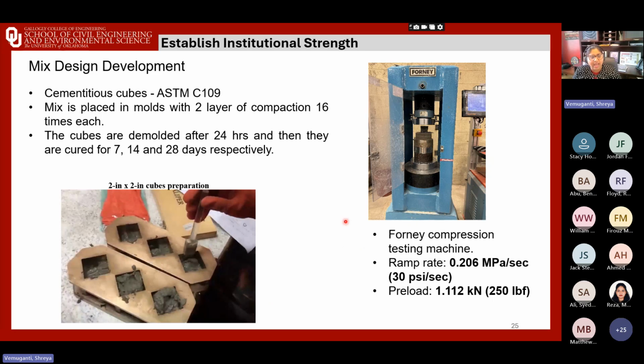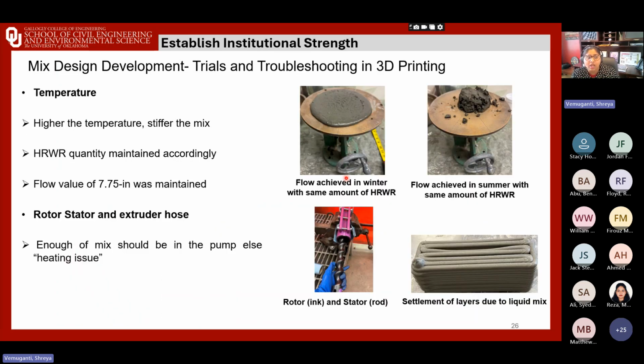So this is something we are showing here. We've made cubes here, one of our very initial specimen fabrications, and we used a compressive strength machine, the Forney, to get these results. Some of the early trials and troubleshooting, if you look at a few of these pictures here: we used high range water reducers in our mix. And with temperature, especially in winter, we would see more flow. And then in summer, with the same amount of high range water reducer, we absolutely saw stiff and clogged mixes. So this essentially would absolutely clog the pump, right?